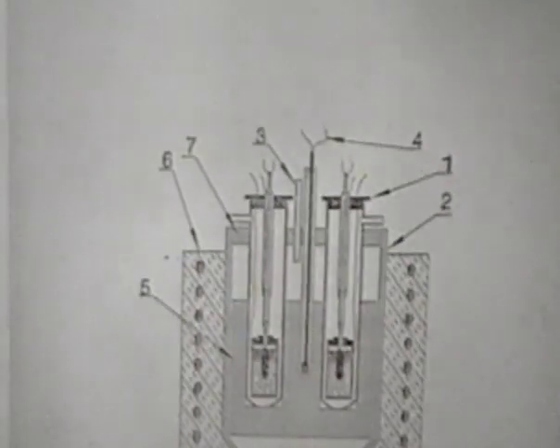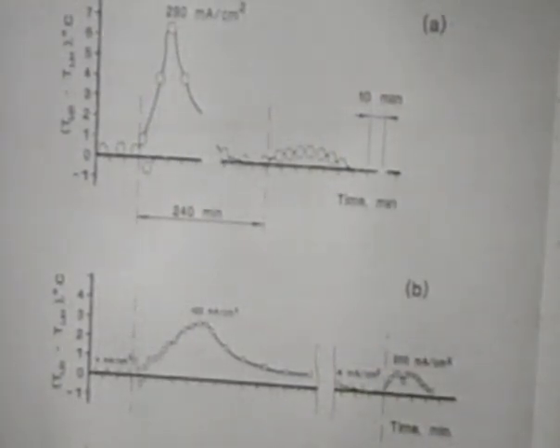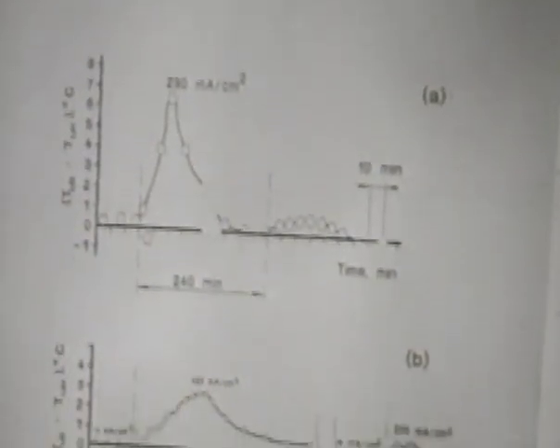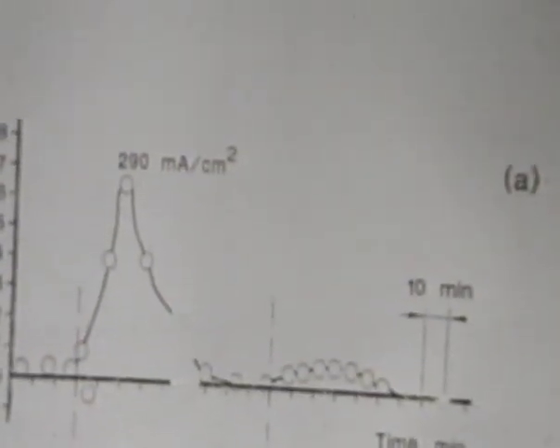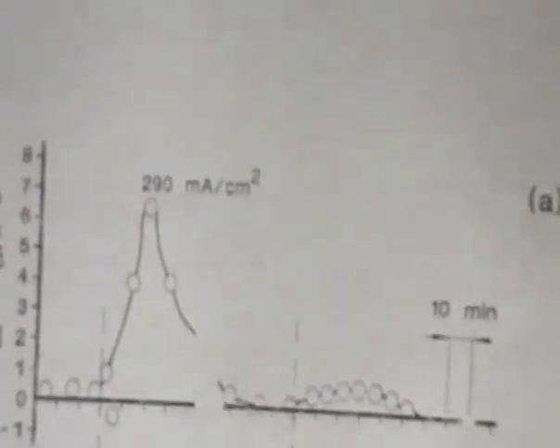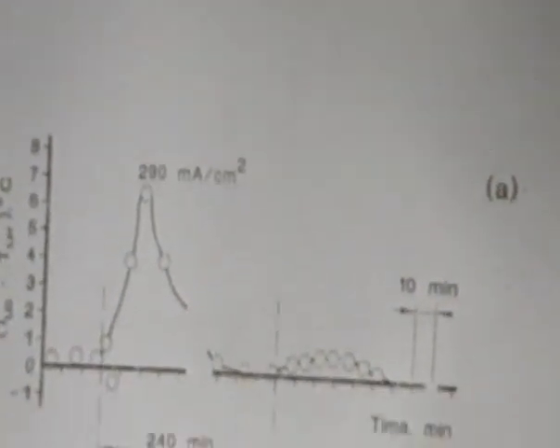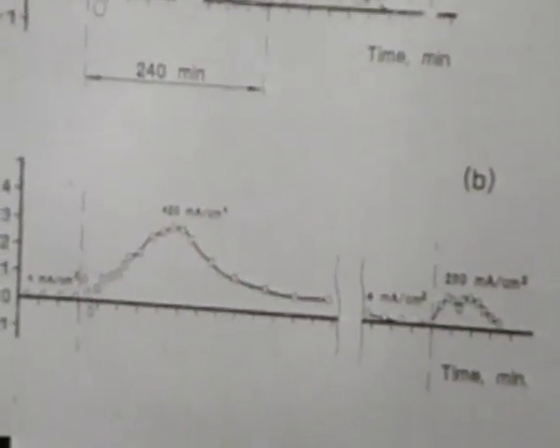Around the oven were placed 2 flat neutron detectors. So this is our first experiment. What did we find? These curves illustrate not temperature, but the differential temperature between the hydrogen cell and the deuterium cell. There is no difference when the current is small and steady, about 4 milliamps per square centimeter, like here. But when we increase the current up to 290 milliamps per square centimeter, we have a very good difference in temperatures. The deuterium cell produces more heat than the hydrogen cell.